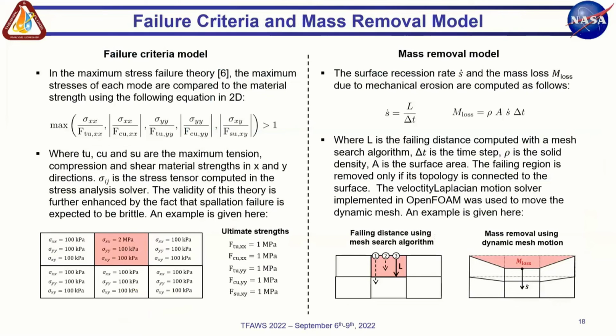Then following with our model, the failure criteria allows us to find the regions where mechanical erosion might happen. The model used follows the maximum stress failure theory, in which the maximum stresses of each mode or direction are compared against the material's strength, following this equation for the 2D case, where FTU and FCU are the ultimate tension and compression strengths in the X and Y direction, and FSU is the ultimate shear strength. Sigma is the stress tensor computed by the stress analysis solver. An example of how this failure criteria is applied can be observed in the figure below.